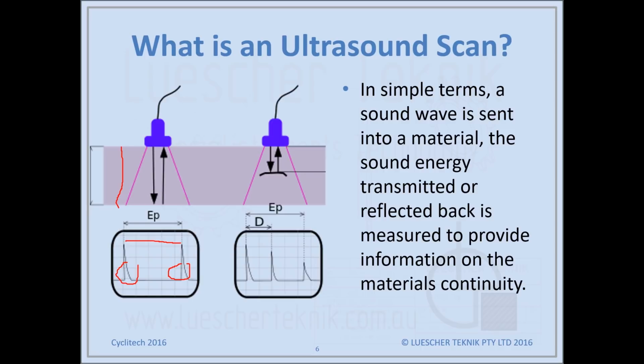On this example here, we've got a defect, and that's represented by this peak here, which is approximately mid-plane. So the sound is reflected off that interface, and that's shown on the oscilloscope trace.